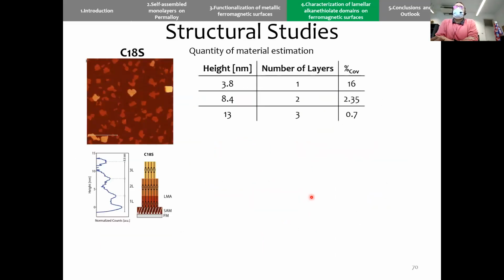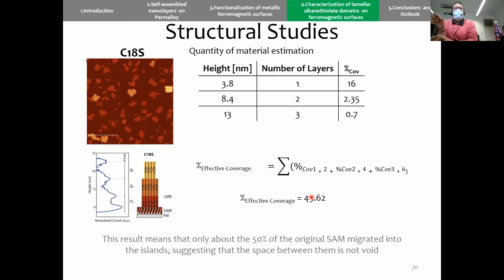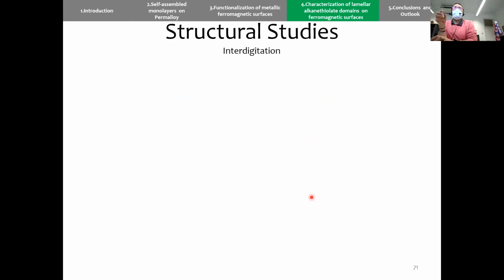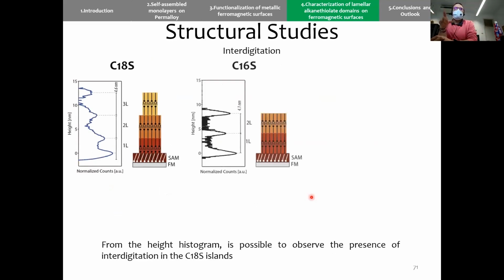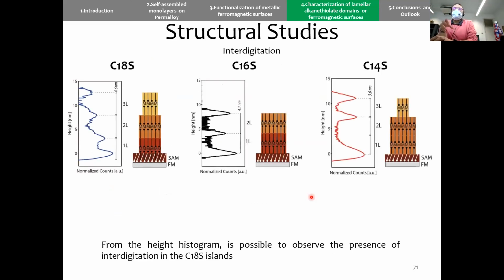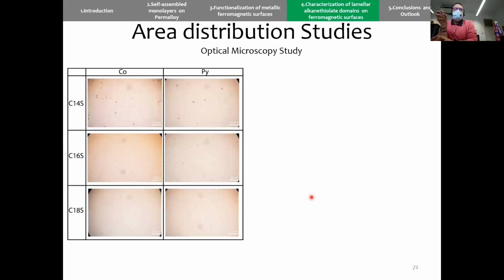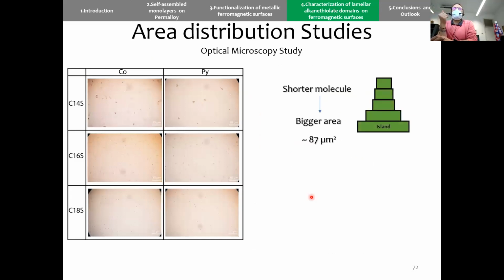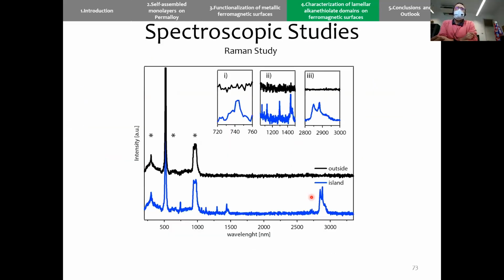We have also observed that some of the material will come from the surface, from the original SAM, and also we observe some interdigitation. So it means that we have something on the bottom and this is growing on the top. And also we observe that shorter molecules tend to have bigger area structures, while longer molecules have shorter areas.